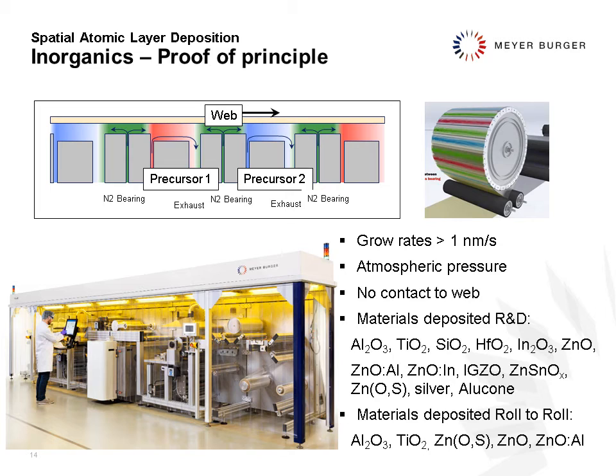Now, it can be done in time, meaning you have a chamber, a substrate, you fill the chamber with precursor 1, you purge the chamber, you fill it with precursor 2, and by repeating this cycle, you will start growing a layer. Now, a possibility to extend this is to use, instead of time, space. So you could have, like in the example above, a moving substrate and fixed chambers where you have only precursor 1 or only precursor 2, but the position of the web will change.